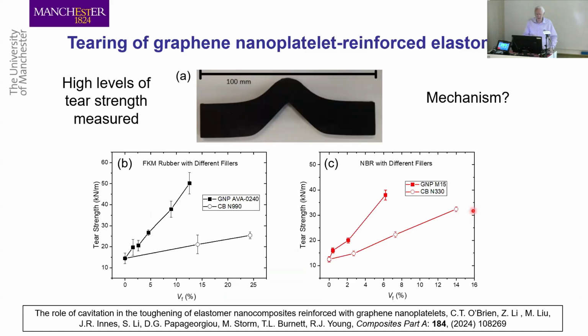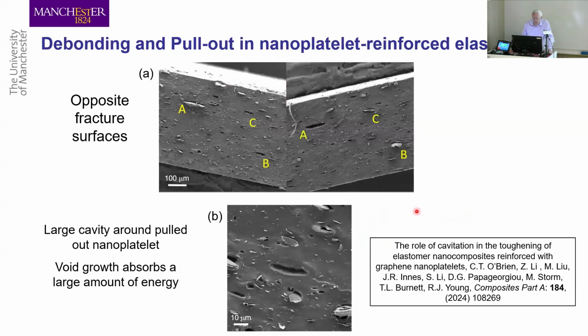And this is an example for an FKM rubber here. We did a tear test for this material. This is our sort of standard tear specimen. It's a rather odd ASTM specimen, but essentially you can measure the tear strength against the loading, much better than carbon black, as you might expect. And you get the slope here, which predicts a very high tearing energy, much higher than you'd expect for debonding and pullout. Something else must be going on.